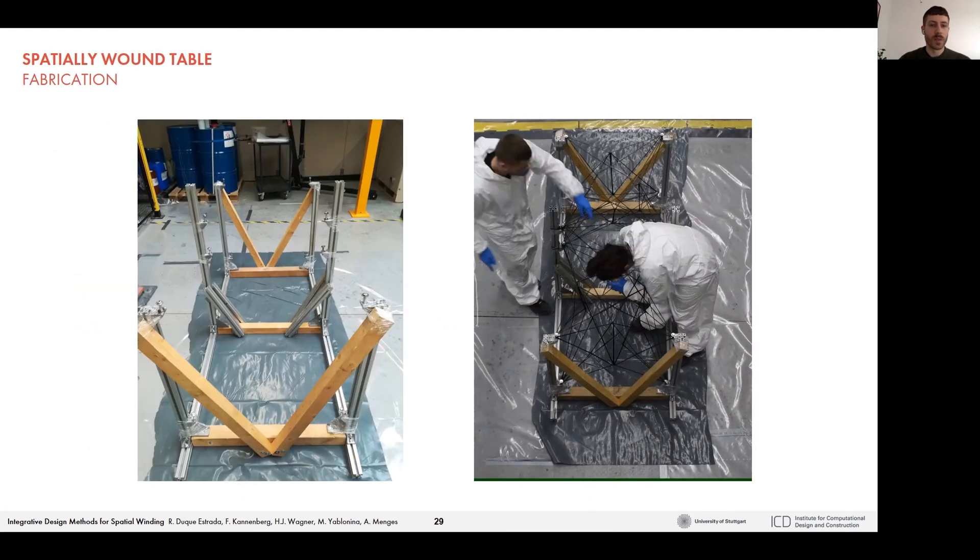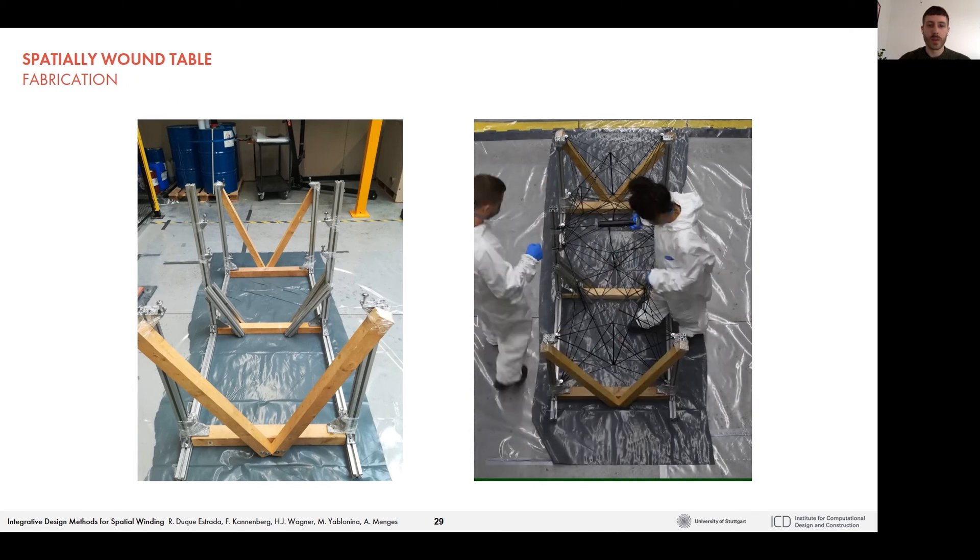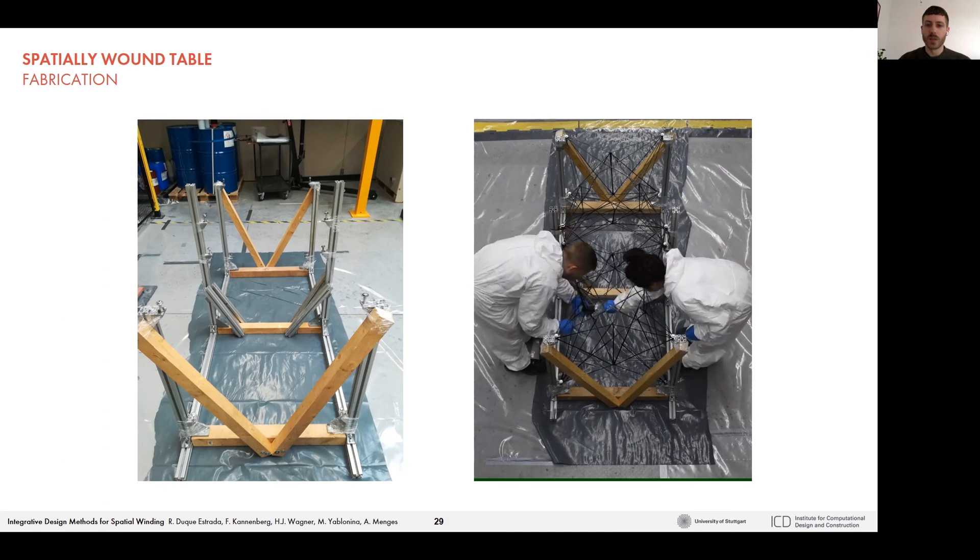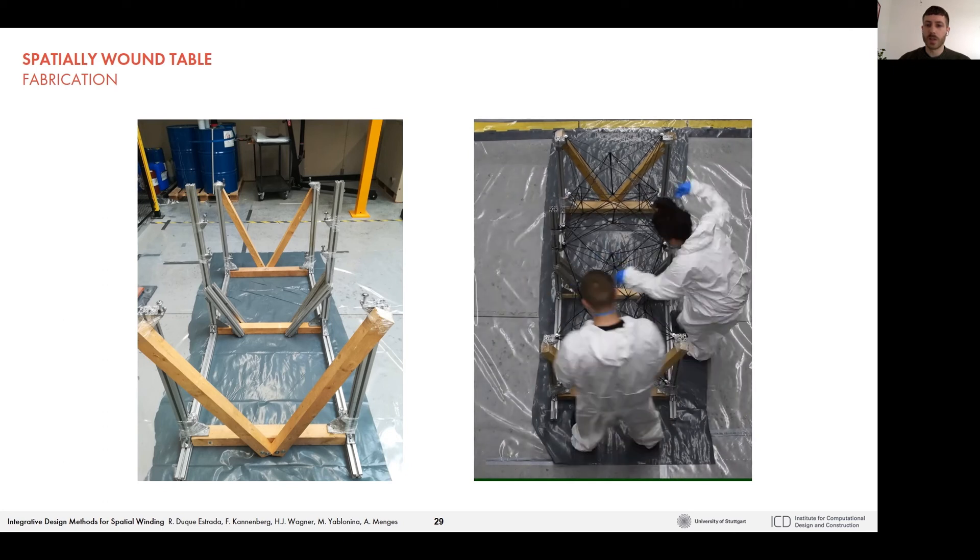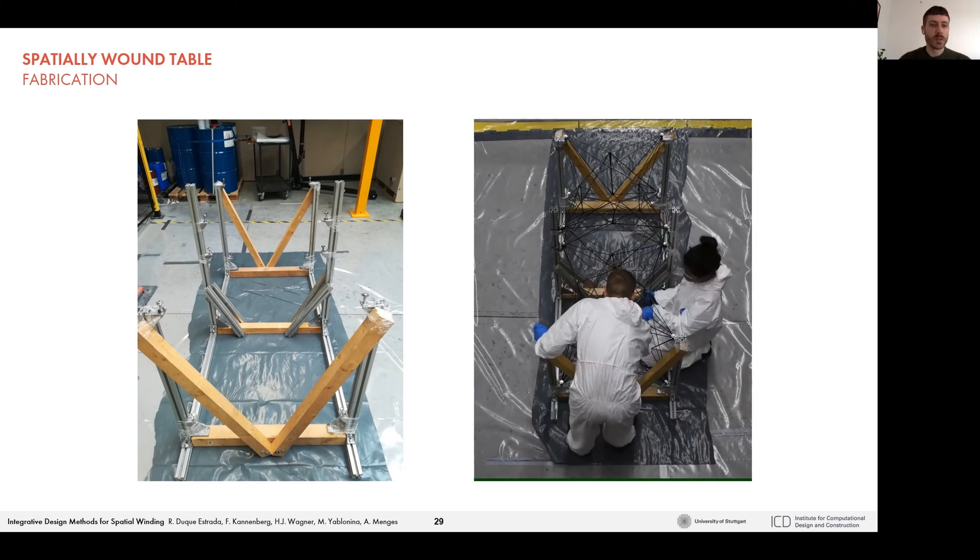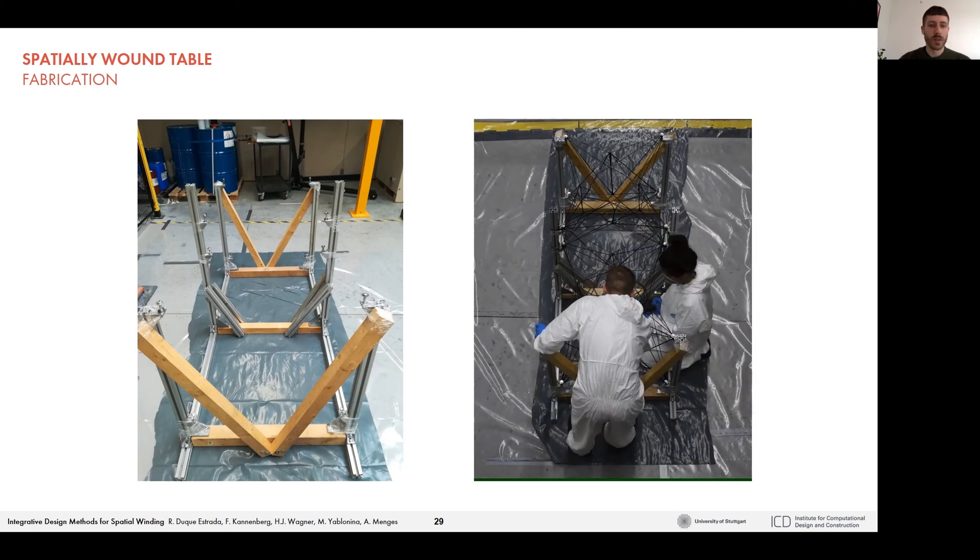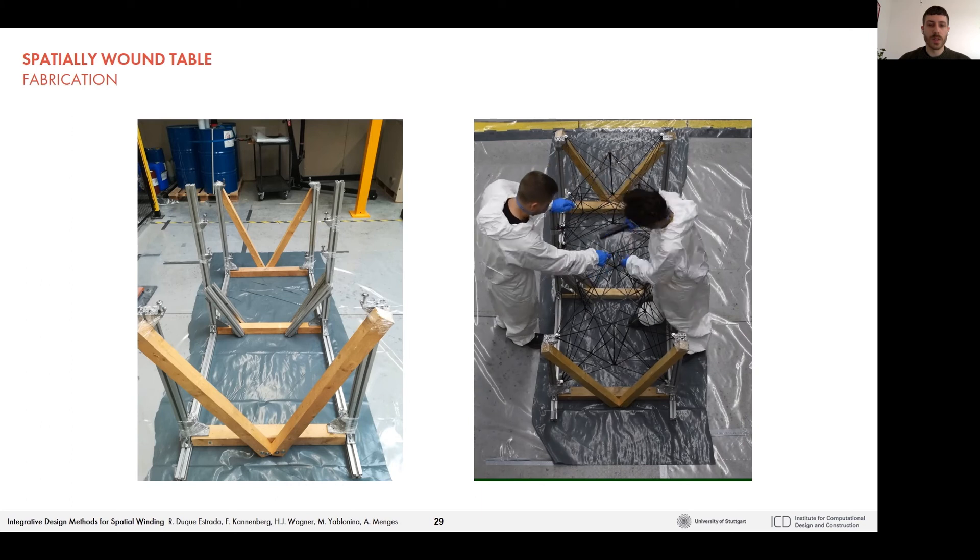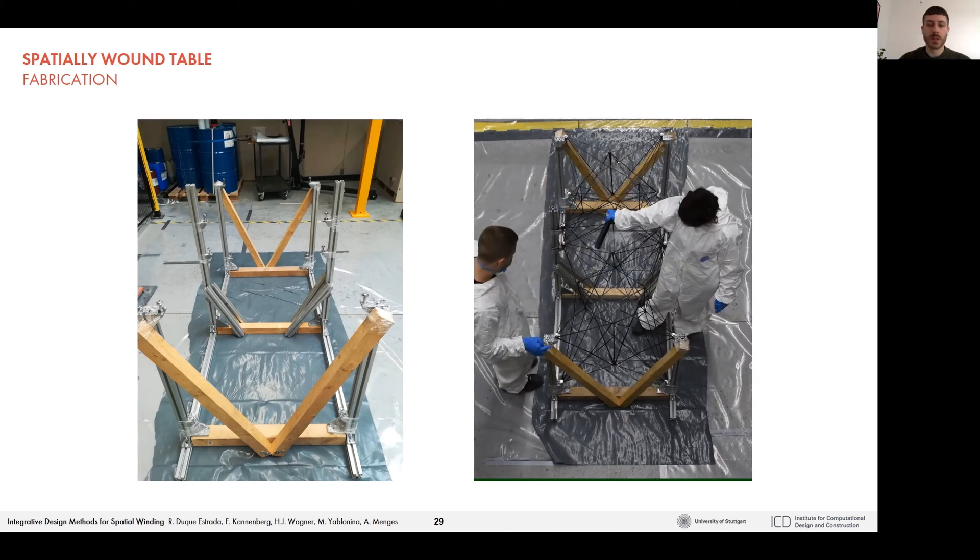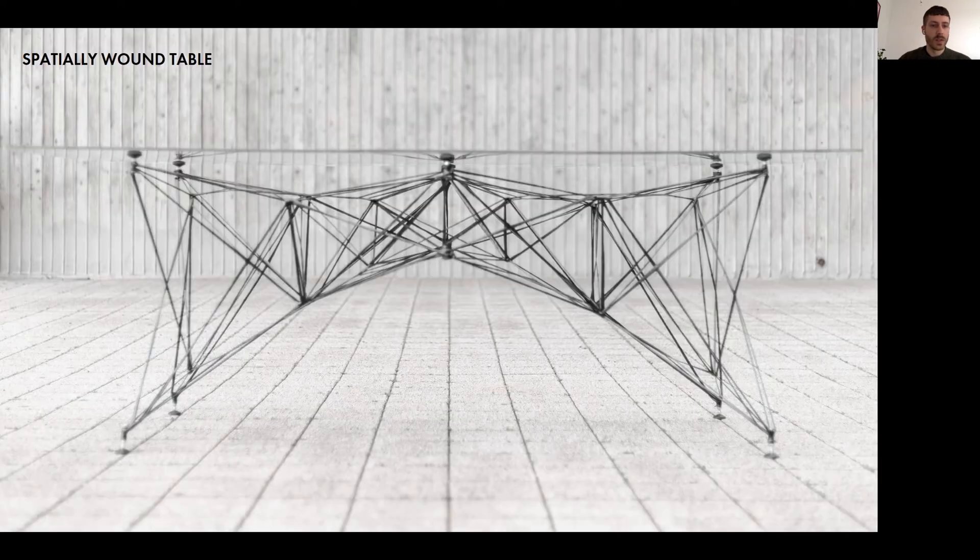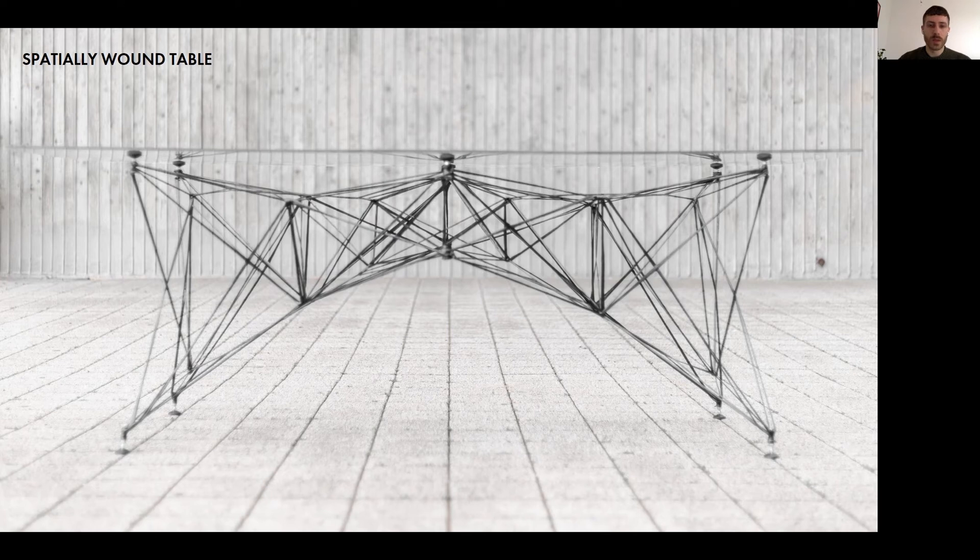The table was fabricated manually in about four hours with a simple frame made of aluminum profiles. Spools with different tow numbers were used, enabling the fabrication with various cross-sections. For the material, we used self-made carbon fiber prepreg which presented good viscosity, enabling the material to slide while keeping the whole setup very clean. After the structure was wound, it was cured in an industrial oven for four hours at 120 degrees Celsius. The final table structure measured 160 by 80 by 75 centimeters and weighed only 1.8 kilograms. An evenly distributed load test up to 60 kilograms showed less than 2 centimeters of deformation.